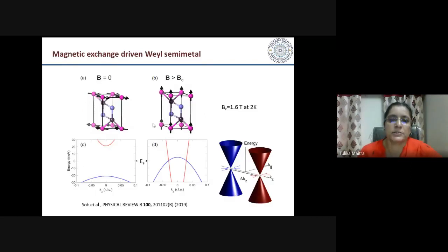And this was indeed established by experiment. Soh and others did ARPES experiments, and they found that in the ferromagnetic state, with spins pointing along the C direction, they find 2 Weyl points at the Fermi level. And this ferromagnetic state is actually very close. I mean, it can be driven by a very small magnetic field, which is 1.6 Tesla. So from the A-type antiferromagnetic state, which is the ground state, one can go to the ferromagnetic state by applying this small magnetic field, which also corroborates our observation that the ferromagnetic state is very close by in energy to the A-type antiferromagnetic state.